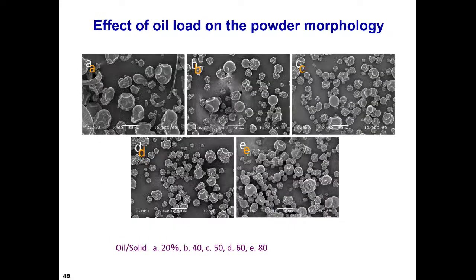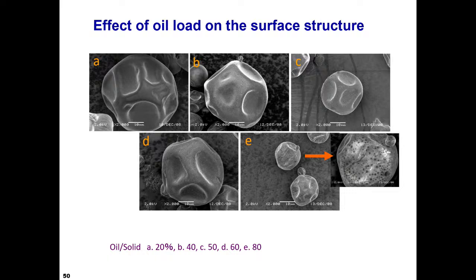So oil content affects the powder morphology, because in the high oil content case, liquid viscosity is lower than the low oil content powder case. So in the high oil content case, we can see the oil droplet on the surface.